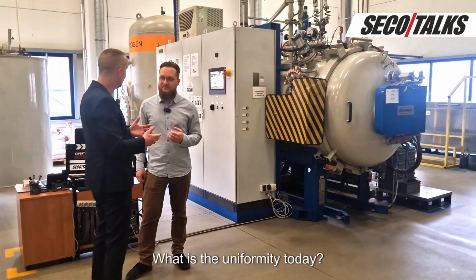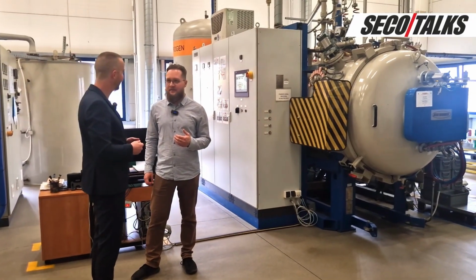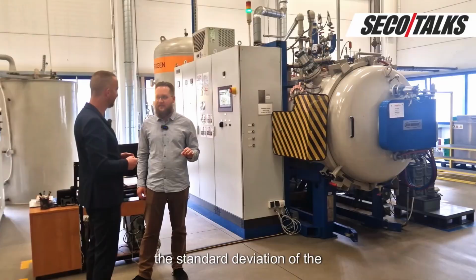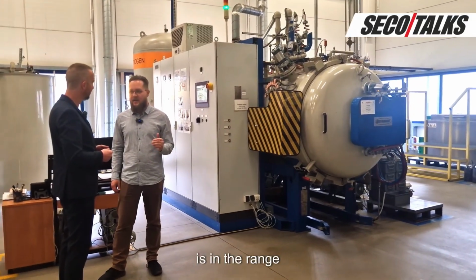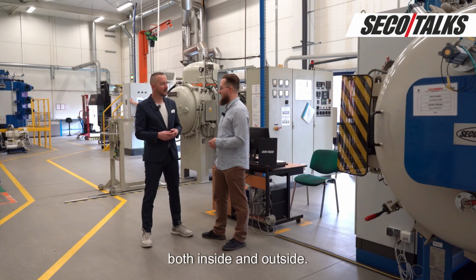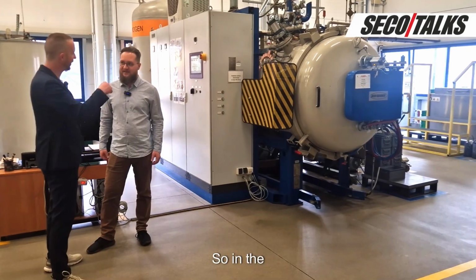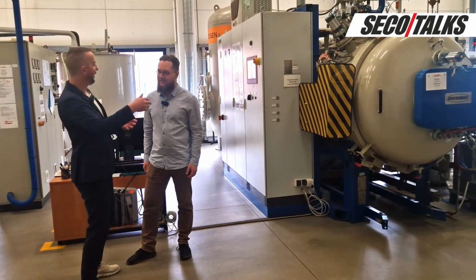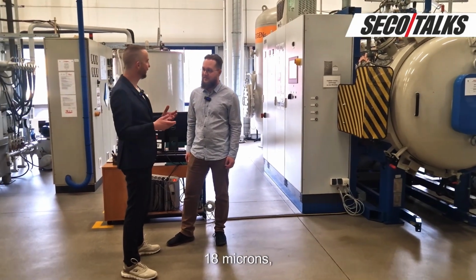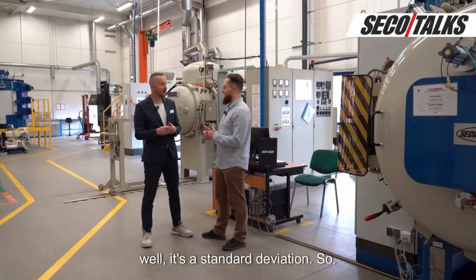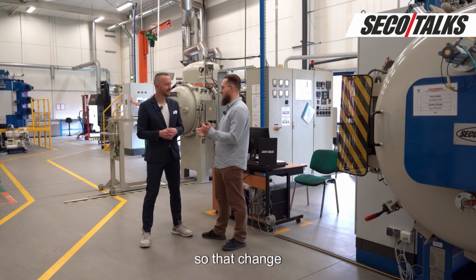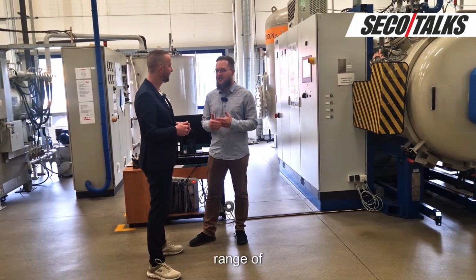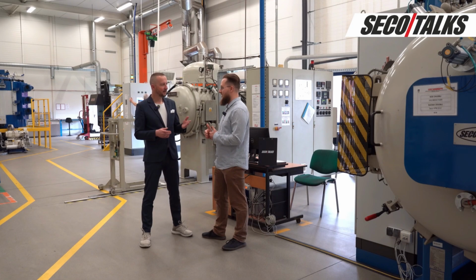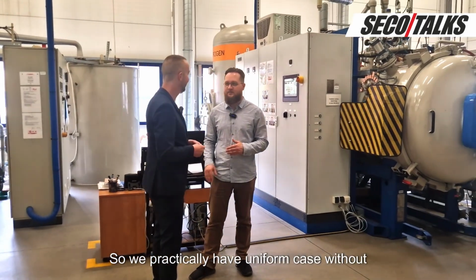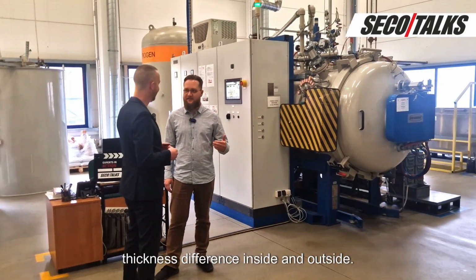So what is the uniformity today? Well, right now, the standard deviation of the effective case depth is in the range of 18-20 microns, both inside and outside. So at the end of the hole and outside of elements, not more than 18 microns. Well, it's a standard deviation. Yes, so the change sometimes can be slightly bigger, but the differences that we observe are in the range of measurement error. So we practically have a uniform case without thickness difference inside and outside.